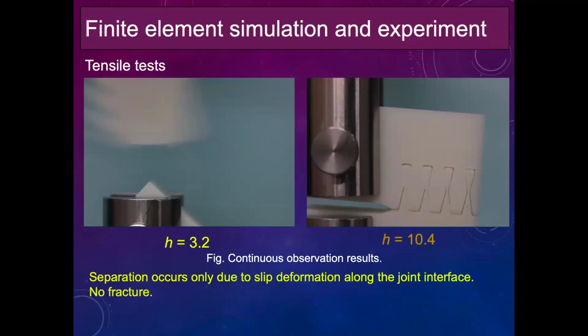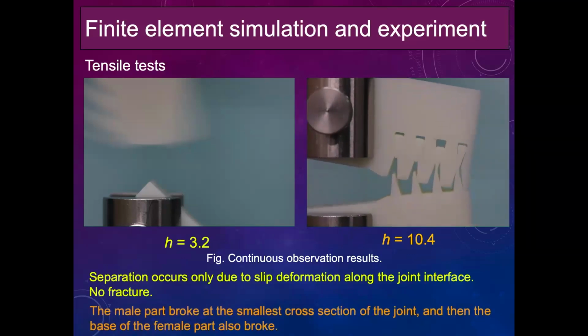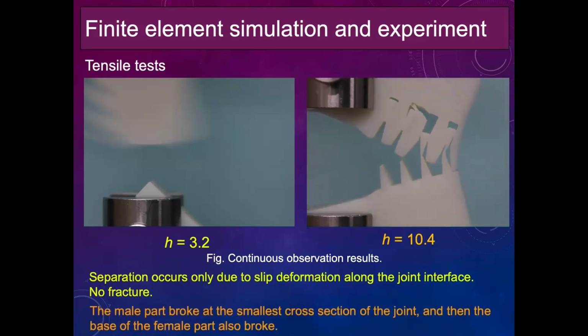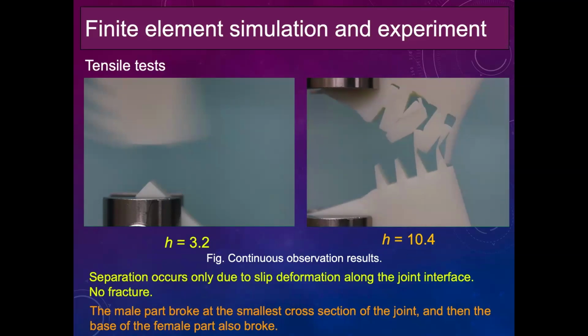On the other hand, when we look at the case for H equal to 10.4 millimeter, from the observation, the male part breaks at the smallest cross section of the sickle joint, and then the base of the female part also breaks. That is a very complicated fracture behavior when the CT specimen has a higher H of the sickle joint parts.